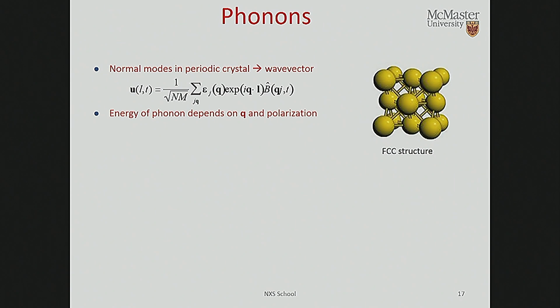Okay, so these phonons, we're going to imagine that the phonons are really displacements from the equilibrium position for the atoms, and it's for all the atoms in your solid. So for every atom, labeled with an index L, there's going to be some displacement for that atom at time t. It's going to go like 1 upon the square root of its mass, and it goes inversely as the square root of the mass because it's like root k over m from harmonic oscillators and such.